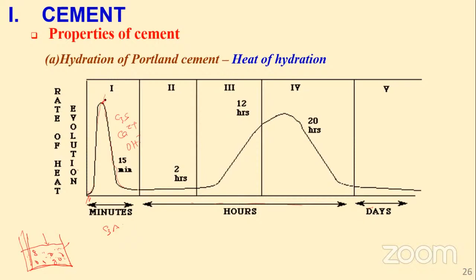However, this hydration process slows down quickly. Okay, what will cause this to happen? So remember, in this mix, the hydration product, the reaction is taking place and the product being formed is still inside here. It's not removed. So this release of calcium ions and hydroxide ions, they are in the mix. And as they continue being released, they are saturated. You end up having calcium hydroxide. Okay. So the system becomes saturated and the calcium hydroxide starts to crystallize. The calcium hydroxide here in this mix starts to form crystals.